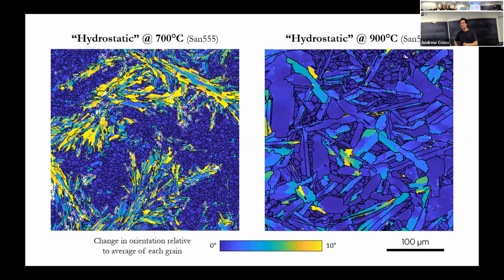And so one of the things that the defects will do is they'll drive grain size reduction. So the idea here is that maybe at lower temperatures, we're introducing more defects, so we're getting more grain size reduction after the transformation's finished. And so that is giving us the weakening that we see in those experiments.